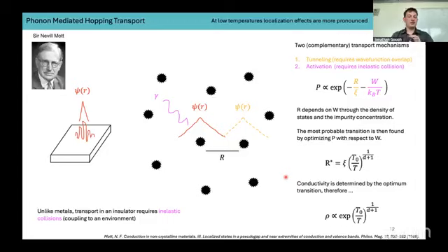This process should continue down to zero temperature as the electron will hop further and further distances, and it shows up in the temperature dependence of your conductivity or resistivity in this case. One thing to note is that this power is quite important because it distinguishes not only the dimension of the system, so here D is 1, but also variations of variable range hopping.